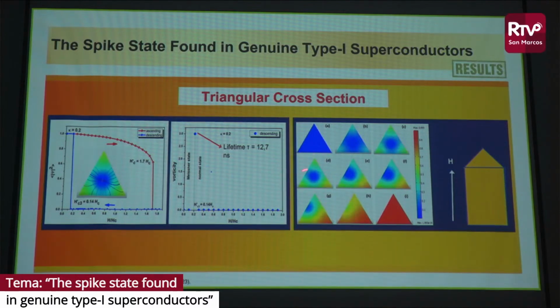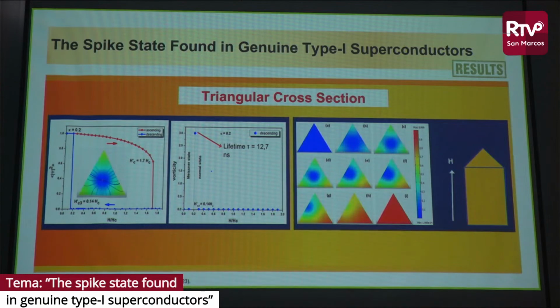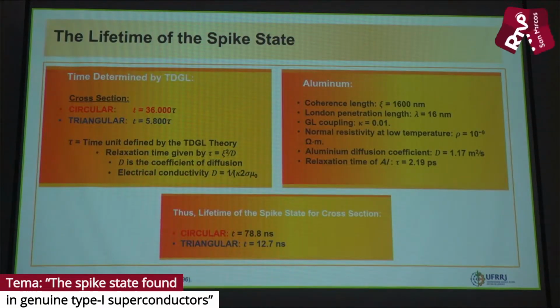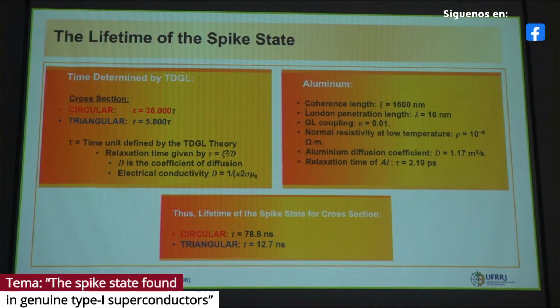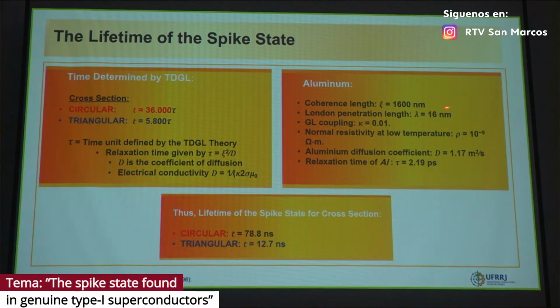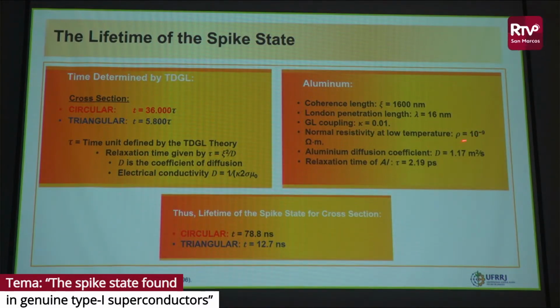Well, so we have calculated the circular and the triangular cross sections. In order to have an idea of the time of this metastable state, I have used the parameters of aluminum. I will show you. Using the parameters of aluminum, xi is 1,600 nanometers, the Ginzburg-Landau coupling has this value, lambda is 16. The normal resistivity is about 10 to the minus 9 ohm meters. The aluminum diffusion coefficient is this. Okay.